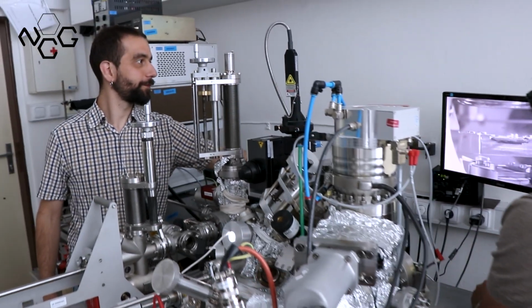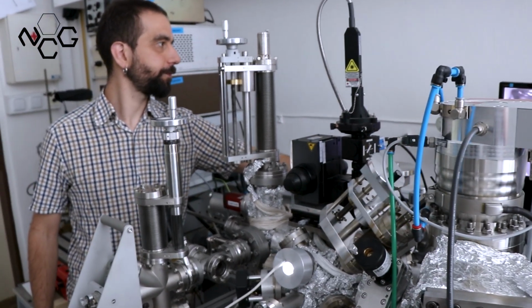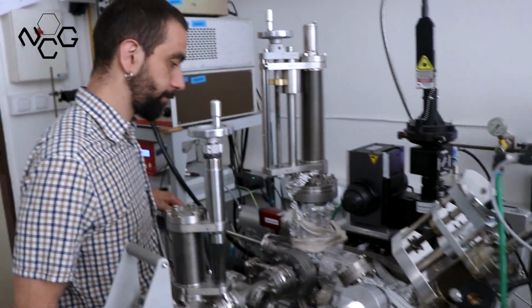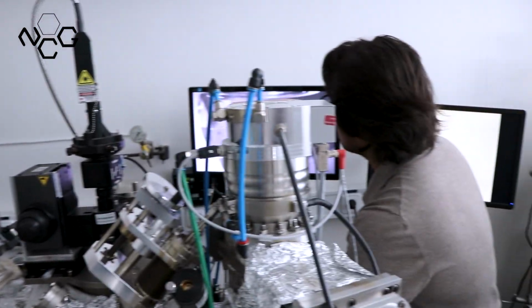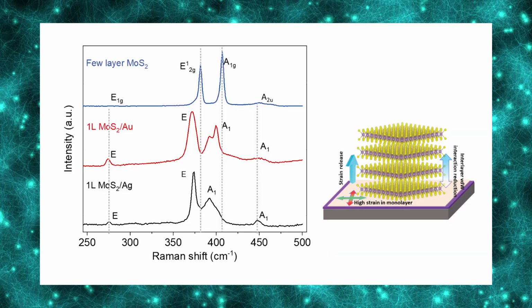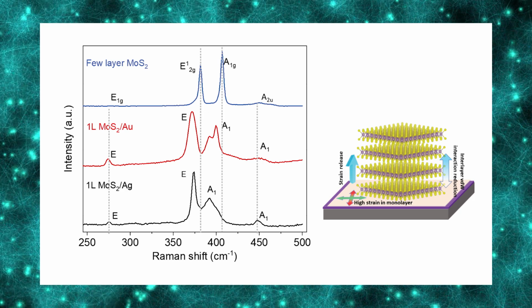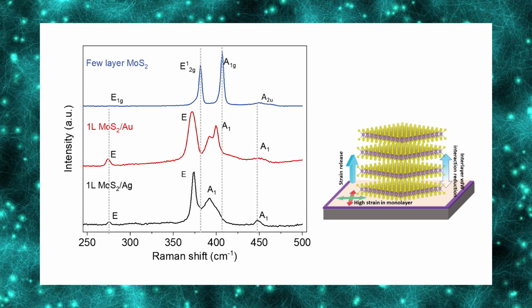To confirm the presence of monolayer MoS2, we measured Raman spectra using our in situ spectrometer. The spectra really showed the expected MoS2 features, with only a shift of the Raman peaks on monolayer with respect to higher layers. We attribute this shift to strain induced by the substrate that is released in MoS2 layers above the first one. This contributes, we believe, to the monolayer selectivity of this exfoliation method.